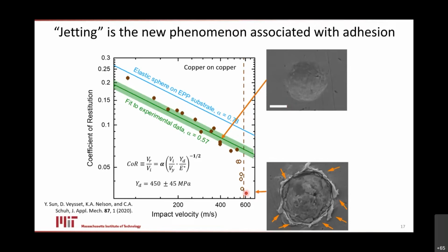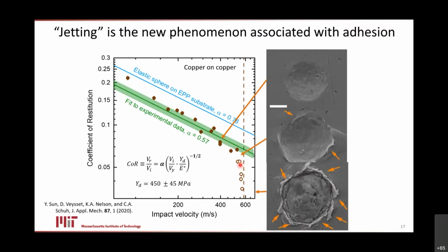Conversely, on this end, when there's very clear jetting going on, this is what it looks like. So this is a particle now with huge lips around the edge, and you can see that material has been extruded up around the edge and shot out of there, right? So that's clear evidence that jetting occurred. And now the interesting question is in the middle. When we diverge from the power law, but before the particle sticks, do we have any jetting? And the answer is we do.